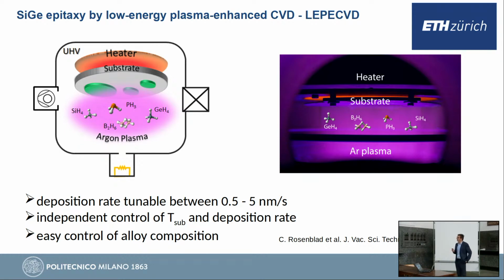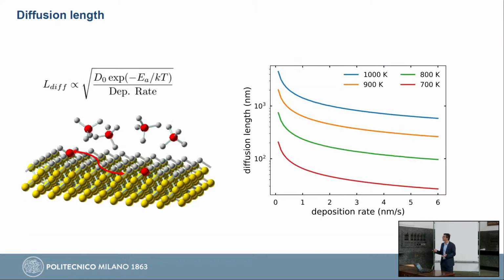One of the, say, peculiarities of this technique, which was developed more than 20 years ago at ETH Zurich, is that actually you can use the argon plasma to tune over a very wide range the deposition rate, so the rate at which you put materials. So we can go from 5 nanometers per second, which is pretty fast, to much lower deposition rate. Why is the deposition rate important? Because essentially, the time a species diffuses on a surface before being incorporated is essentially inversely proportional to the square root of this deposition rate.